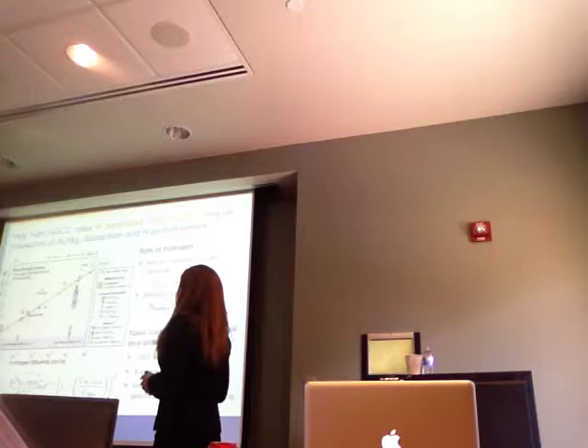So we considered, what if there's no traps in the microstructure? What could your fastest hydrogen diffusivity be in aluminum alloys? And that is about 10 to the negative 7 centimeters squared per second. So we plotted our sensitized data at this point, and we noticed that this fit very well. But how can you actually explain this very rapid crack growth rate?